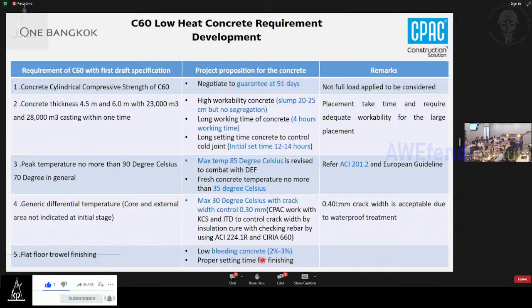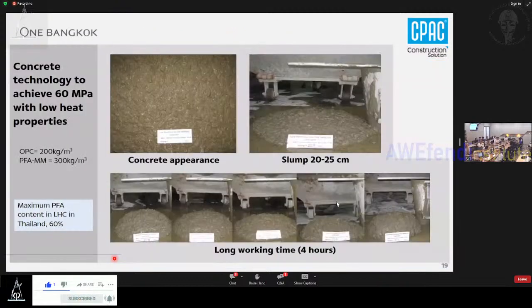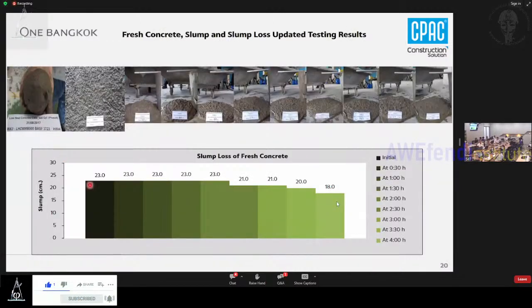And we need low bleeding concrete, because after they cast the foundation, they will trowel on the surface to make a car park area, so they don't need to do a topping again. This is the thing that we are working on. You can see here we developed the concrete for this one. We use 60% PFA or fly ash to replace the cementitious material. The cementitious material for this one is around 500 kilograms per cubic meter. And this is how the concrete looks, and you can see here the slump retention at 4 hours.